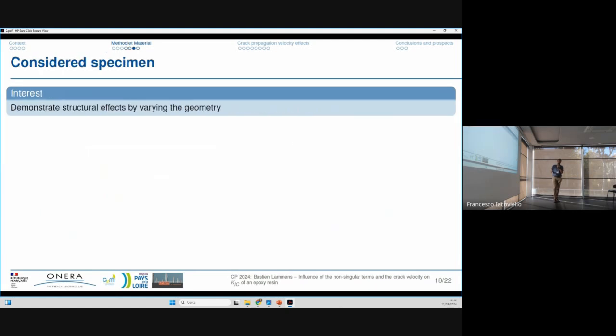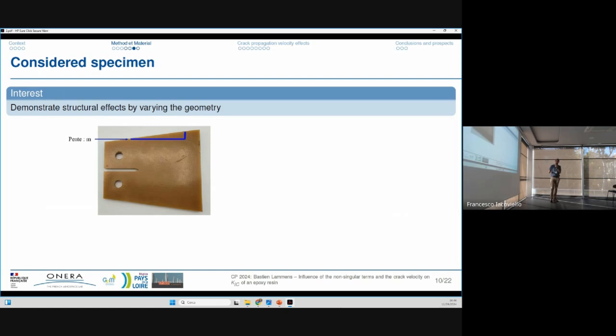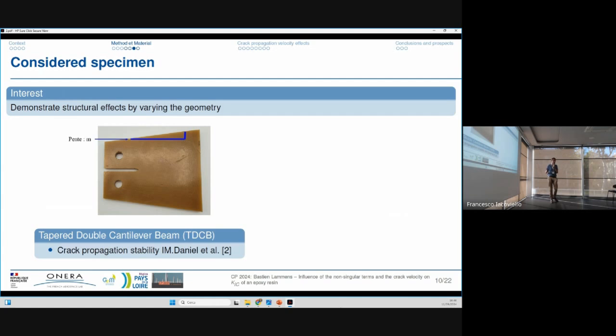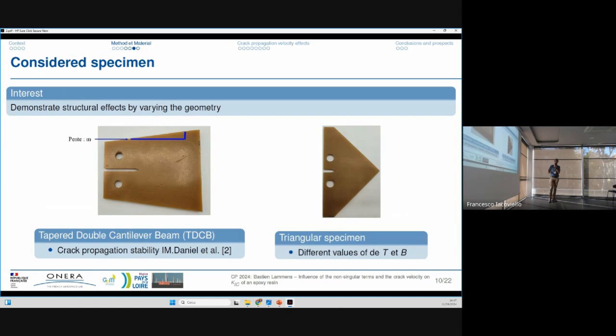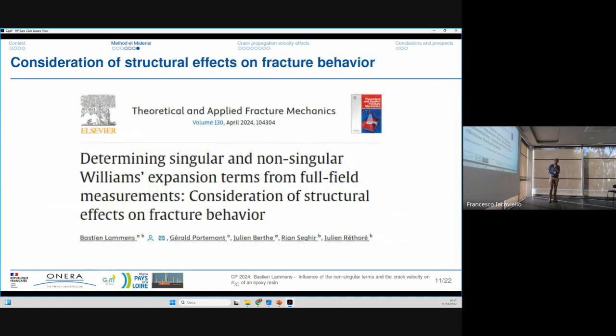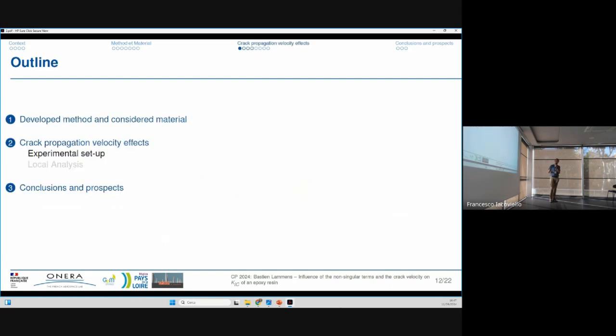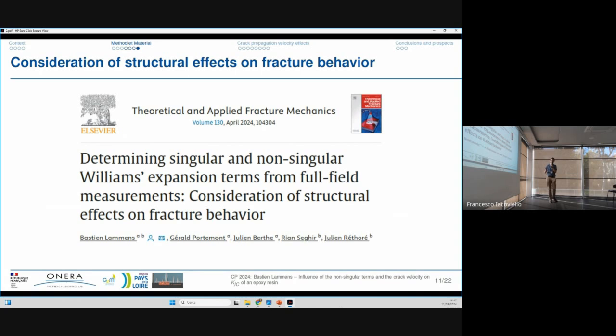So to demonstrate the structural effect, we use different geometries, different specimens. The tapered double cantilever beam, TDCB specimen, where we have crack propagation stability according to the literature. And we chose another specimen, a triangular specimen, with different values of T and B. The consideration of structural effect on fracture behavior has been studied, and a paper was written at the beginning of the year about this point. So I want to mention the result of KIC static and the different version of the paper.